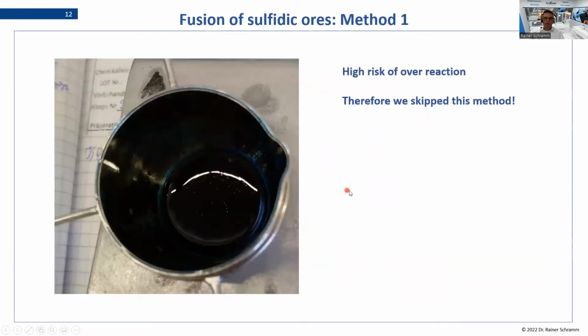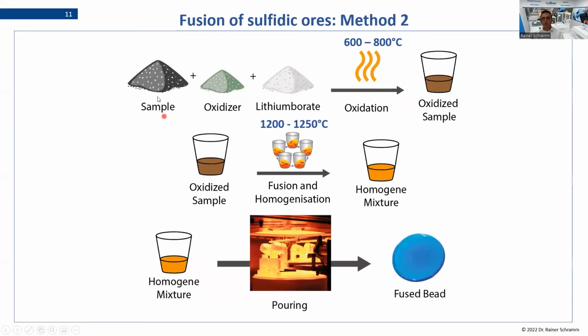Method 1 makes some trouble because very often it overreacts. So that, like you see here, the whole crucible is now spilled with sample oxidizer mixture, and it even went outside. So this is a bit difficult to get under control. This is why over time we skipped that method and we just use this method as the real stable method in the daily work.